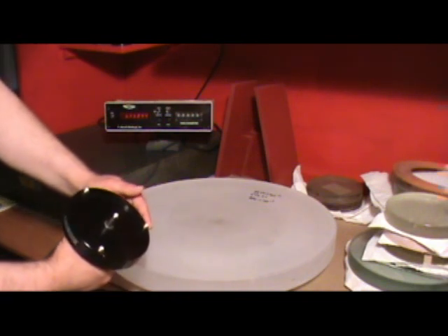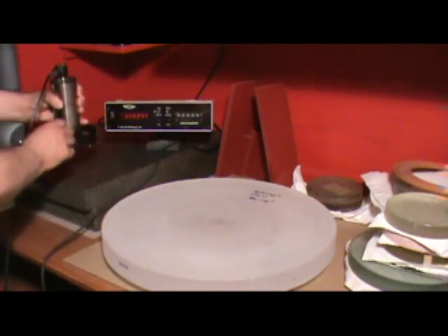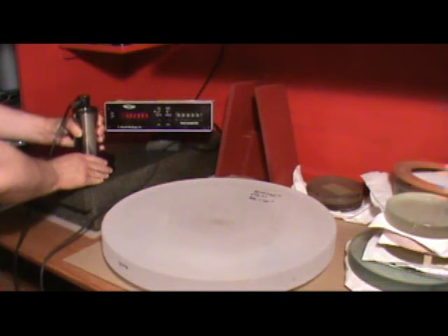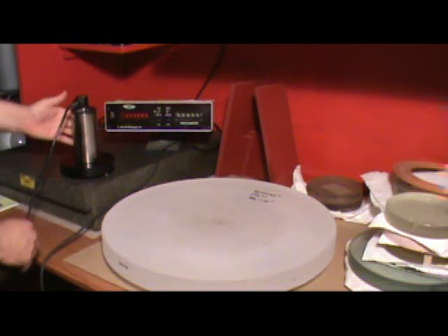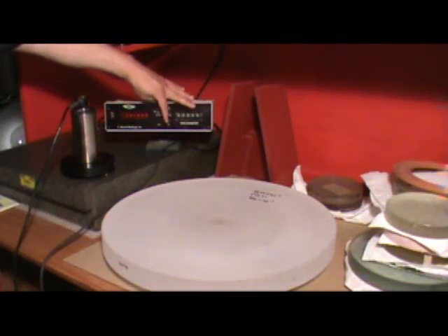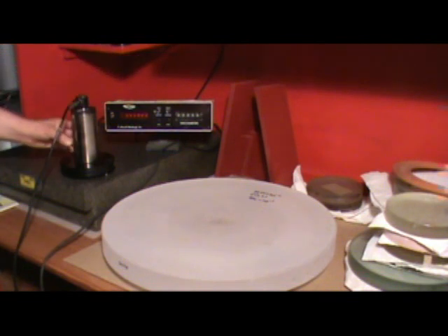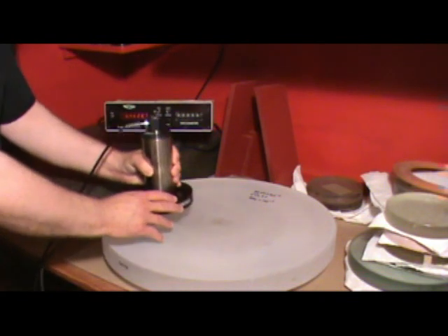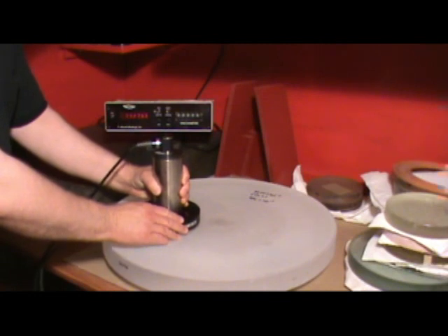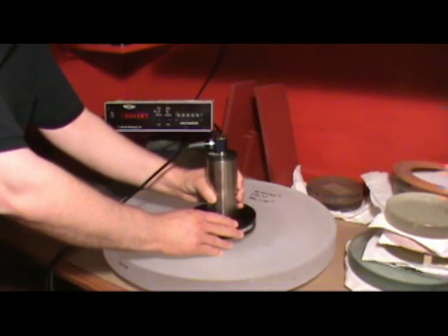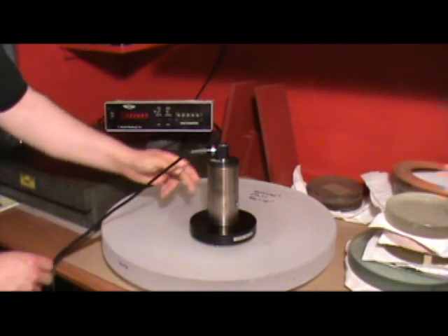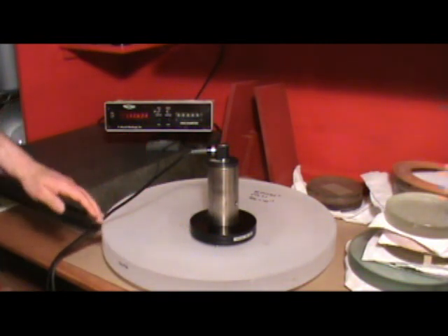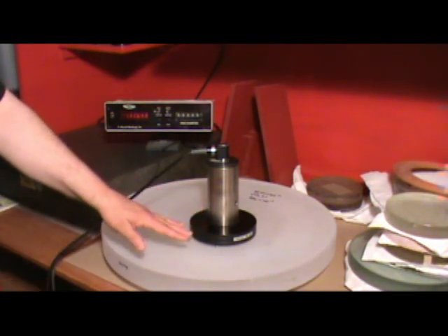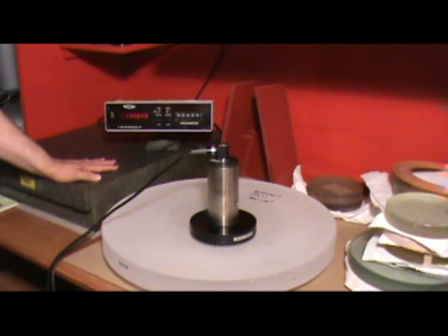the three feet here on the bottom of the spherometer define a plane. So I put the spherometer probe on the surface plate and zero my machine. I'm telling it now it's on something flat, and then when I put this on the mirror, at that point the spherometer will measure the actual depth of the probe below that flat reference.